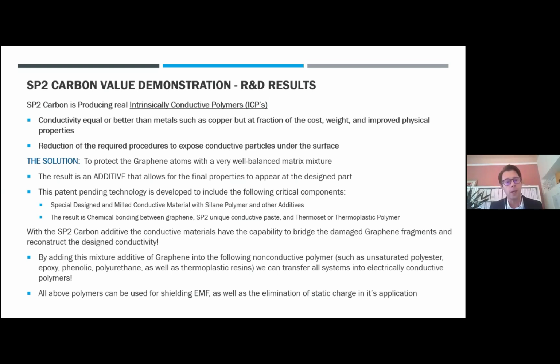We also have developed this technology starting obviously with the experience that we have on the thermoset side, but we also expanded into water-based systems, acrylics. We also see that phenolic, especially when it comes to train application, like Tim mentioned before, when it comes to flame, the combination of phenolic and graphene and their application is a significant advantage that we are really looking into and having very good results on moving into that technology. And again, it's all about the right balance of mixtures when it comes to graphene, additives, and also making sure that they function in the process along the way.